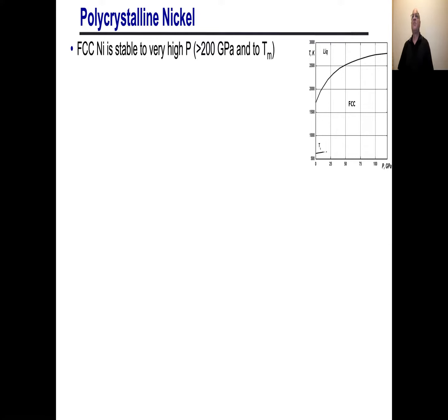Let me show you some recent data on some polycrystalline nickel from the group in Shenyang, IMR. So first, let me just remind you about nickel. If you take nickel and put it under hydrostatic stress to very high pressures, it just stays FCC, and the estimate is up to about 200 GPa and all the way up to the melting point. I'm not sure I believe the 200 GPa number, but the point is that nickel really wants to be FCC and nothing else.